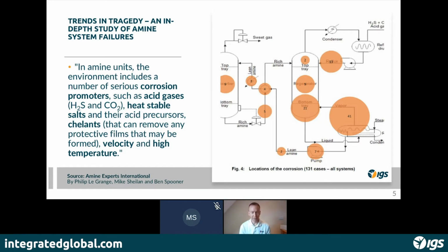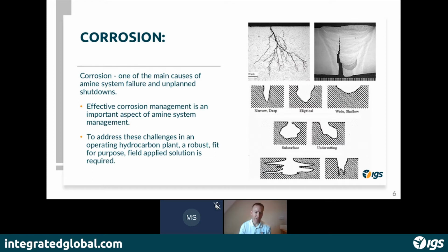H2S poses other challenges. H2S obviously is an acid gas. H2S can lead to problems such as cracking, sulfide stress cracking, acid attack. And in areas where you have low velocities, you can have deposits. Under those deposits, you can then create dissimilar environments, low oxygen contents, and have something similar to galvanic corrosion taking place. So all of these areas in the amine systems have risks, and those risks can lead to corrosion.